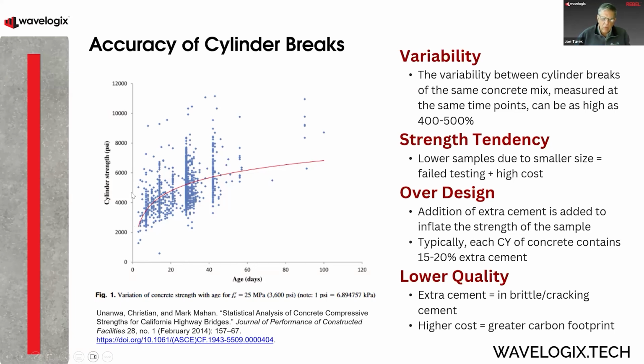And if you look at the compressive strength of that aging concrete, they had over 200 trained technicians make cylinders, crush them on a periodic basis, and then report their findings. And these dots represent what they found at that particular time interval. And you can see it's all over the map. There's almost 400 to 500% variation from what a true strength was to what the technicians were reporting.